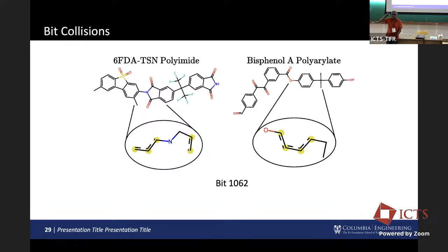We've been taught to believe that tacticity really matters, and it does for many properties. But for gas separation, this is sort of the question he was asking me earlier, it appears not to be important. I don't understand that result. It could be a physically important result, in which case we should explore it. My suspicion is that the permeability data we are using is uncurated from the literature. So the error bars are so big, you've lost the ability to distinguish between subtle features like enantiomeric differences, tacticity differences, crystallinity differences, chain length. None of those things seem to matter. It's just picking up the most obvious thing, which is differences in monomer structure.